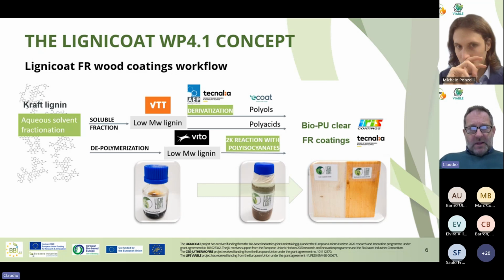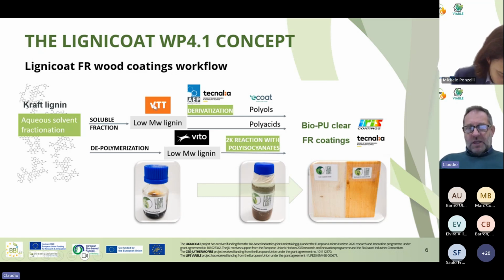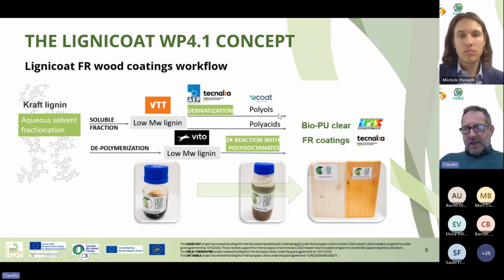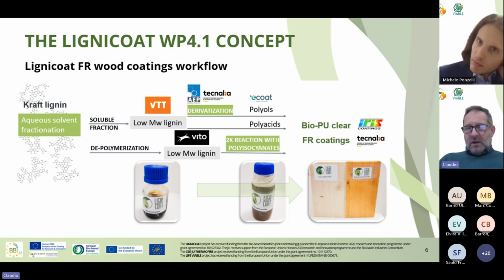We went through a long journey. We have been using different types of lignin derivatives, both soluble fractions obtained by solubility fractionation at VTT and other types obtained by depolymerization at VITO. In all cases, we have got as raw material for our studies this low molecular weight lignin, and at the beginning, we actually got resins that were made through polyols and polyacid derived from lignin, incorporated into a resin that we were expected to use as a binder, single component or two component. Only in a later step, we learned that we were able to directly react low molecular weight lignin with isocyanates in a two-pack system and to obtain coatings in that way.